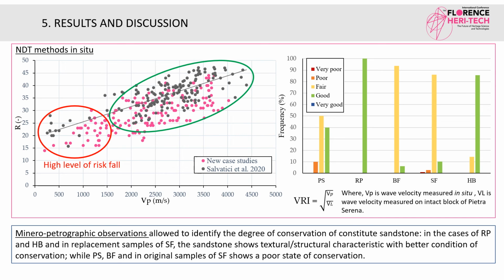The low Vp and R values are contained in the red cluster, associated to poor state of conservation, low mechanical properties, and to presence of wetness zone of the stone. Falling into the red area are the corbels of Pucci-Sansedoni Palace, Salone delle Feste Palace, and one corbel of Badia Fiesolana. The quality of Pietra Serena corbels was provided by calculating the velocity ratio index.